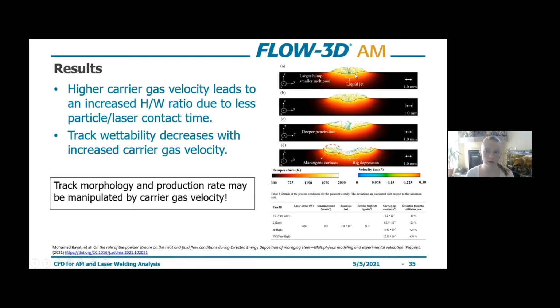So what's an important takeaway from this study is that track morphology and production rates can be manipulated by the carrier gas velocity. So usually we're looking at power or speed to kind of change the dimensions of our tracks. But in directed energy deposition cases, we have that additional parameter that we can look at, the speed of the carrier gas velocity, which has quite a big impact on the morphology of the track.